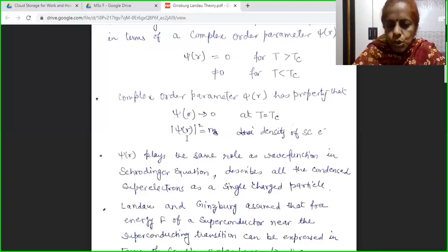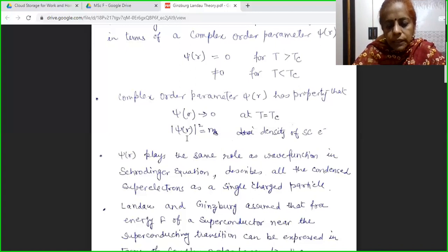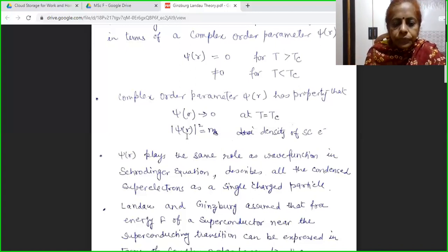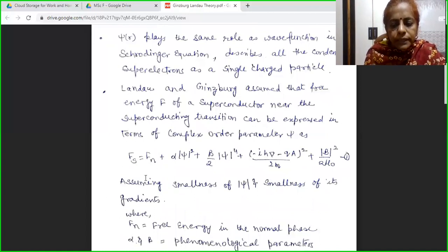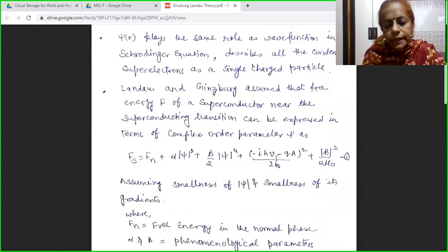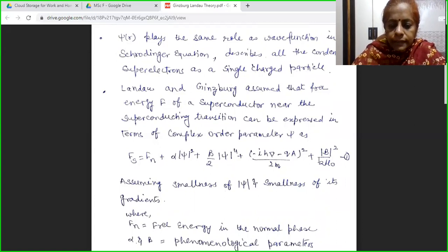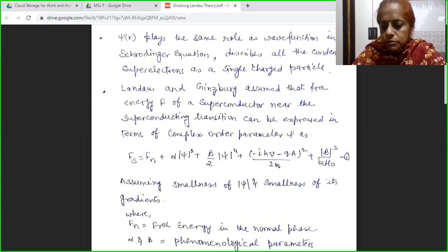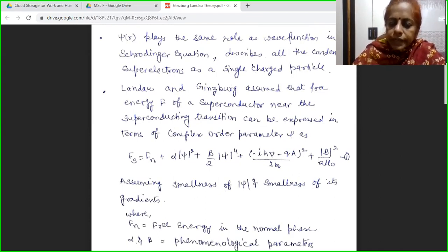Using this complex order parameter psi, scientists Landau and Ginzburg assumed that the free energy of a superconductor Fs can be expressed as: Fn plus alpha times psi square plus beta over 2 times psi to the power 4, plus the term involving minus i h-bar del minus qA, this whole squared over 2m, plus mod of B squared over 2 mu-zero. Here we have neglected higher order terms of psi, and the smallness of its gradients is assumed.